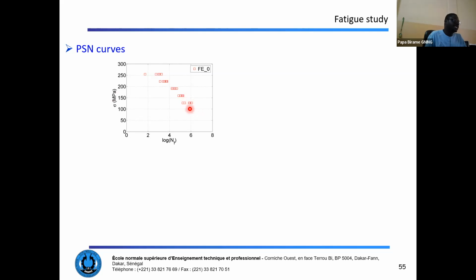we can plot the Wöhler curve, the average one, which corresponds to the 50% probability of life of the specimens. And we can make the result more confident by increasing the probability level to 80 to 98% probability of failure of this specimen in tensile loading fatigue.